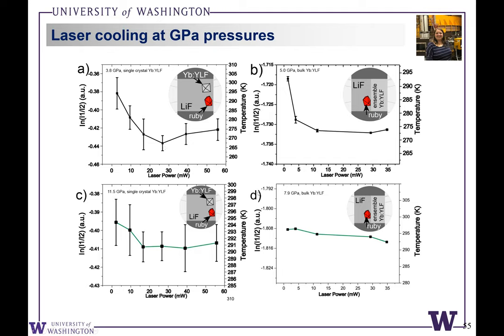But interestingly, we can also do experiments not just on a single particle level. We can do experiments with a fully loaded diamond anvil cell and also go above the phase transition pressure. We can go up to 7.9 GPa. And I apologize, I didn't mention this before, that we've got the ratio plotted on the left and the temperature plotted on the right. If you go above the phase transition temperature, it's not as much cooling, but we can see statistically relevant drops in temperature. We have enough signal to noise to claim cooling on the order of 4 or 5 degrees below the starting temperature after the phase transition.